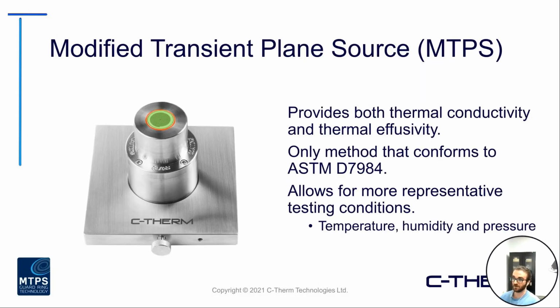And all of this, we'll be focusing on the measurement through the modified transient plane source, or MTPS, which Adam had detailed earlier. A few notes: it provides both thermal conductivity and thermal effusivity measurements. It's the only method that conforms to ASTM D7984, and we'll get into that a little bit here. One of the main benefits of the MTPS and transient methods in general is that it allows for more representative testing conditions. A couple examples: humidity, temperature, pressure. These are different factors that can and will influence these types of thermal measurements, and being able to fine tune your testing geared towards the most representative conditions is going to give you the best possible results for your specific application.